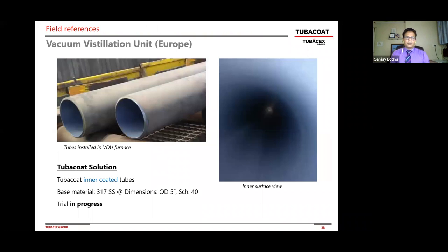Another vacuum unit furnace in Europe has been running close to 2 years now without having to decoke. We don't have any data other than it has not been out of service. It has not gone into decoking. Again, 317 stainless steel, OD is 5 inches, schedule 40. And you can see the tube surface. Trial is in progress now. It's close to 2 years.